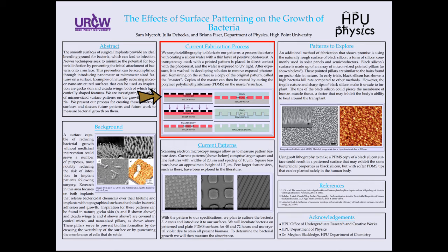Our pattern, printed on a clear transparency, is then placed on top of the sample and exposed to a UV light. Photoresist not shielded by the pattern is then washed away in a developer solution, leaving behind our pattern as a 2-micron high raised surface on the sample. We call this sample our master copy.